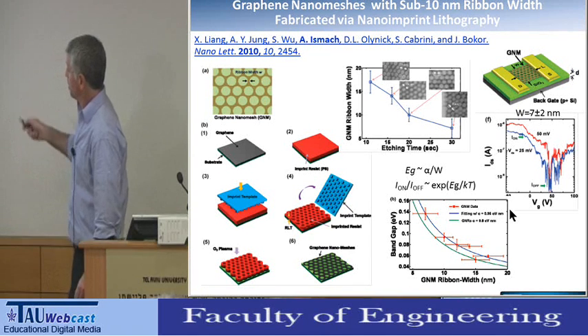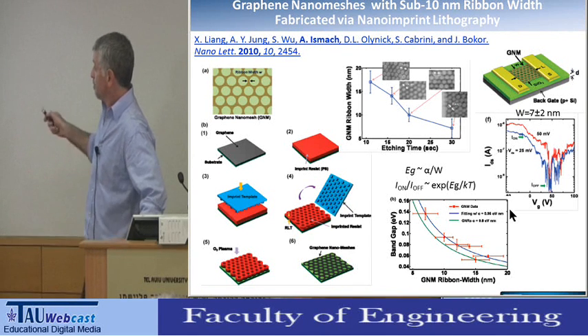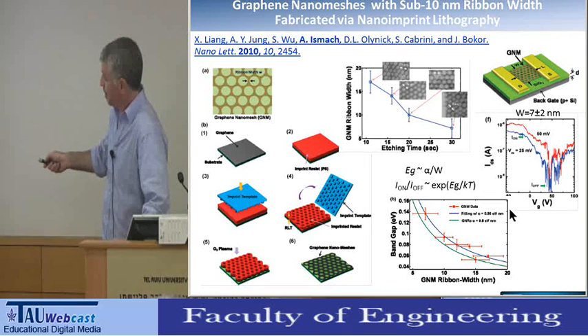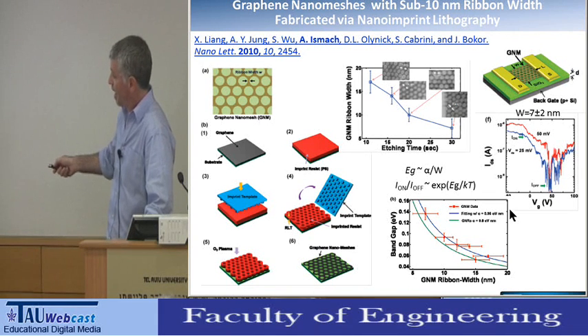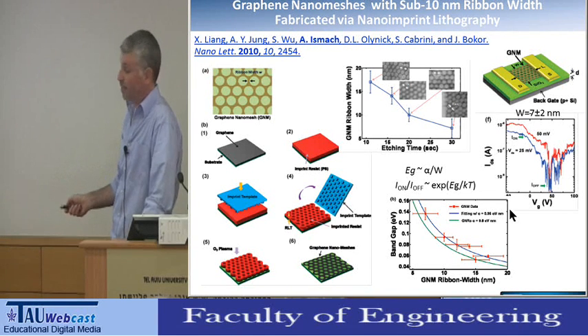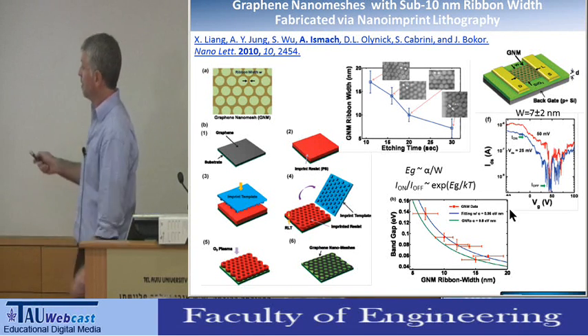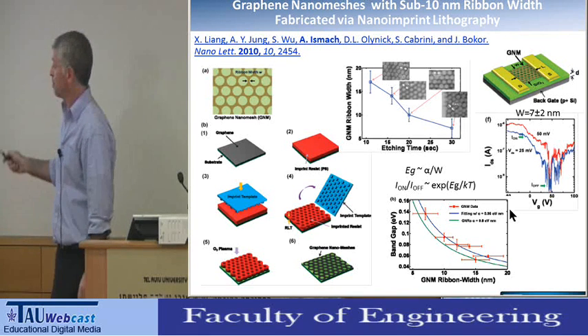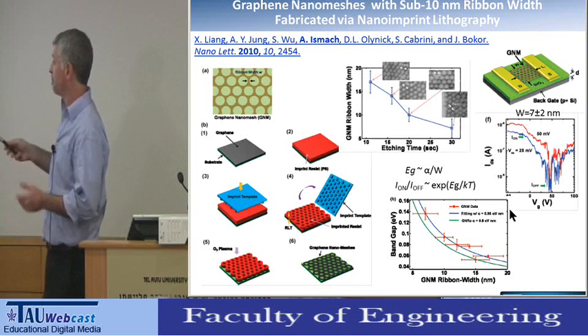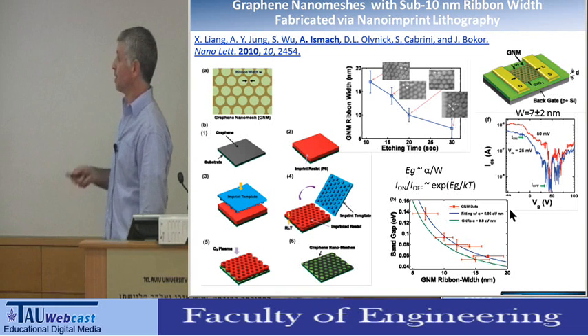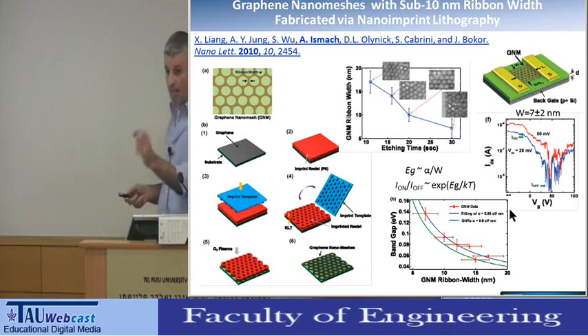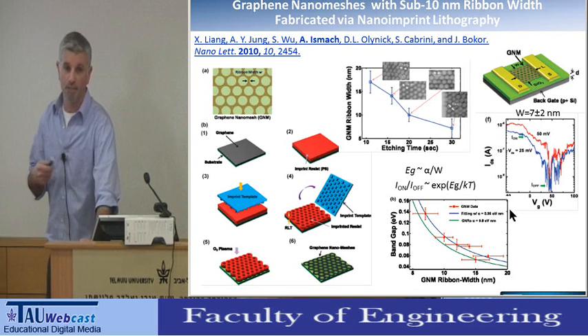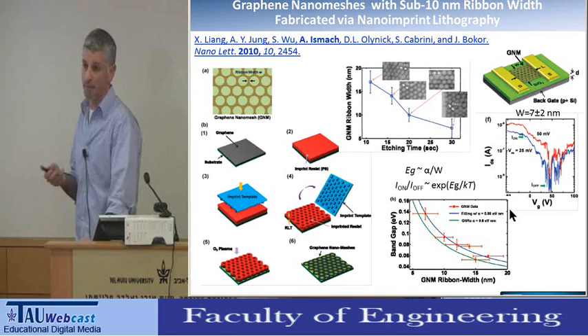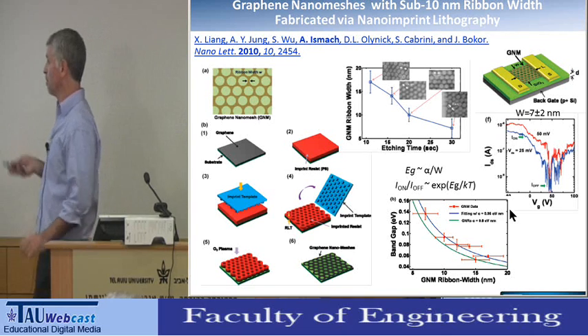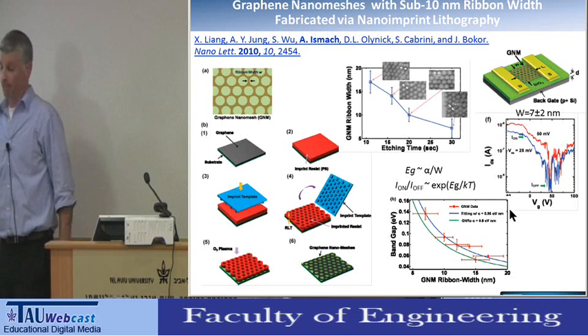And then we, of course, characterized them electrically, and we could see an increase in the band gap. We could see that we could have control over the band gap as a function of the nanoribbon width, as you can see from these formulas. In principle, the band gap is related to 1 over the width of the nanoribbon. And this is similar to the case of the nanotube, in which the band gap of a semiconducting carbon nanotube is related to 1 over the diameter of the tube.